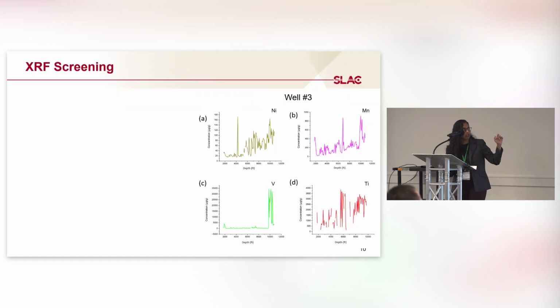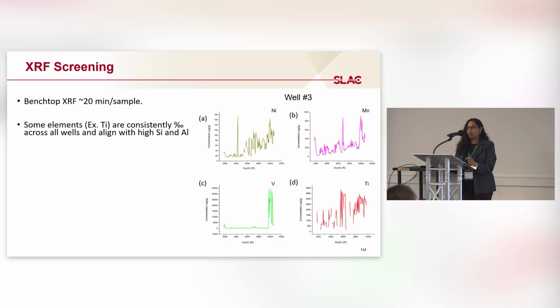So the first one, the X-ray fluorescence screening, which was the elemental analysis. So this would give the elemental composition of the sample. I have a representative sample on the right-hand side. I don't have all the plots because it'll be too much. So what we saw was there were some elements like titanium and other transition metal elements that were consistently present, and these aligned with silicon and aluminum throughout the samples.